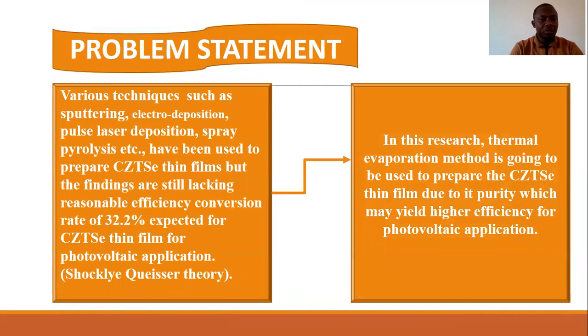Problem statement. Various techniques such as sputtering, electrodeposition, pulsed laser deposition, and spray pyrolysis have all been used to prepare CZTSe thin films, but the findings are still lacking the expected efficiency. A conversion rate of 32.2% is expected for CZTSe thin film for photovoltaic application, as per the Shockley-Queisser theory. In this research, therefore, the thermal evaporation method is going to be used to prepare the CZTSe thin film due to its purity, which may yield higher efficiency for possible photovoltaic application.